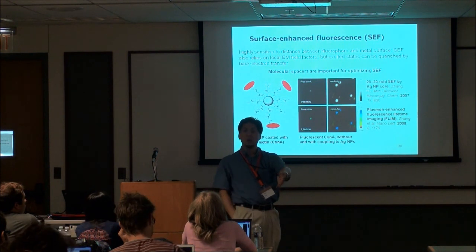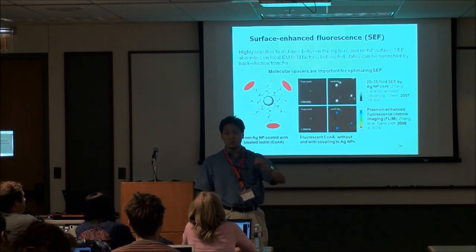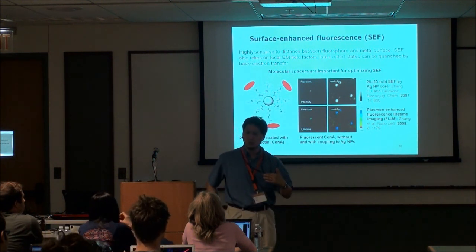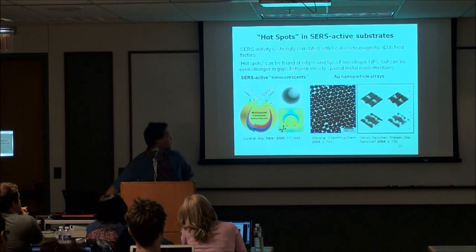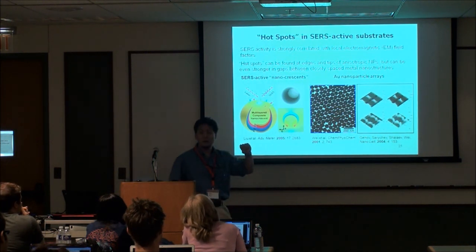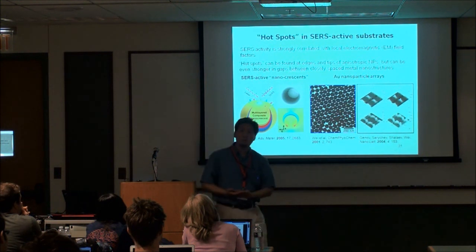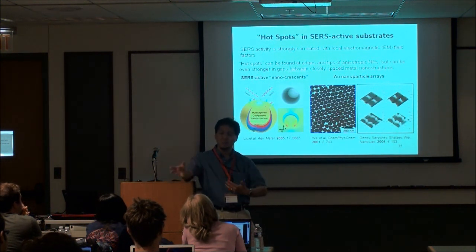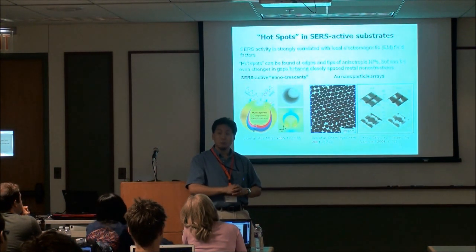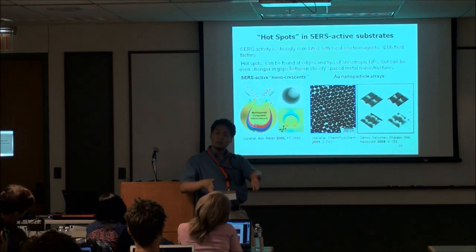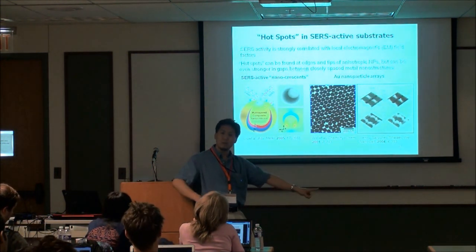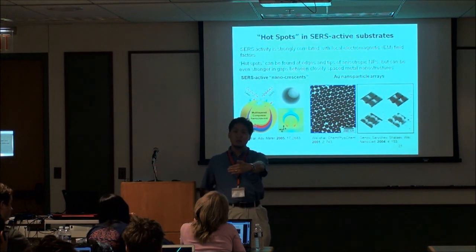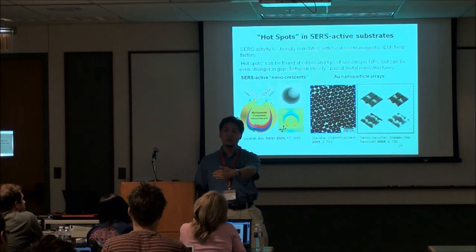There are basically two rate laws. One of them is the rate law of back electron transfer. If a molecule is on the surface, that rate of electron transfer is pretty much exponential if I recall correctly. But for the surface enhancement, the field emission, go back to the picture that has some fields on it. The field can extend out by a few nanometers, and that corresponds to, if I remember correctly, something like an inverse power of 3. Of course, there are also some finer details about whether you have a resonance coupling between the molecule and the metal that it's embedded on. But if I can just give you broad numbers, I would say starting at about 3 nanometers, you're already in the regime where you're enhancing the signal over some negative back electron transfer. And once you're about 10 nanometers, then your plasmon enhancement starts to die off considerably.